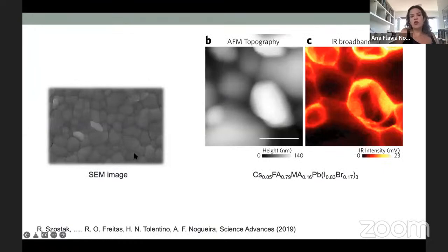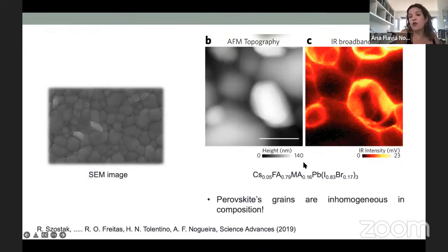So this is the same image that I showed you before, and this is what we call the infrared broadband image. This is the AFM topography on the left. On the right, let's take this grain of the perovskite. What you see is that the intensity of the scattered infrared is different. I believe it is more intense in the grain boundaries. What does it mean? If it's more intense, it means I have fewer molecules absorbing the infrared light. In our case, it's the organic cation. So we believe that close to the grain boundaries we have a depletion of these organic cations located on the side of the perovskite. The conclusion is that if you look at just one grain of perovskite, in terms of composition it is very, very inhomogeneous.